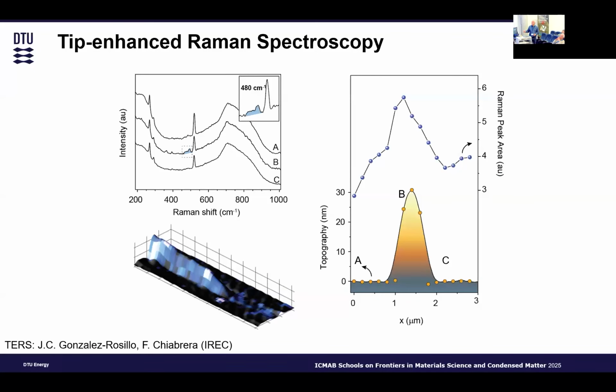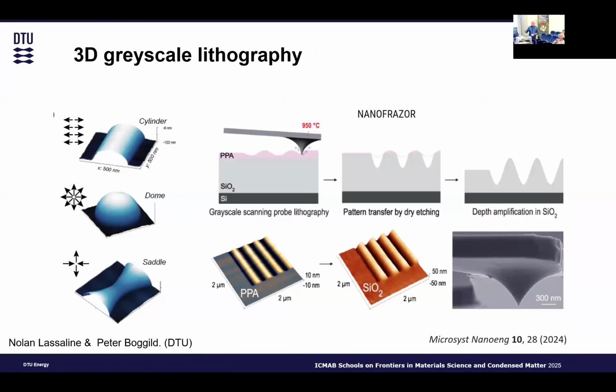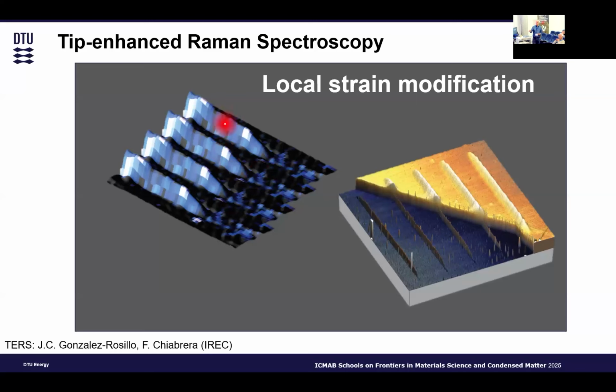So taking this into account, what we did is we took our nanowires and we looked at different positions, A, B, and C. A and C are equal. These are the flat surfaces. So at A and C, we see no signature. And at B, we see a signature at the right position of the first order Raman mode. We think that it is like this. We're still trying to understand the effect, but when we did the tip-enhanced Raman on the sample, we can see that the response of the Raman is different. So we see the different response, and these lines correspond to the first order in the Raman. So these are indications.